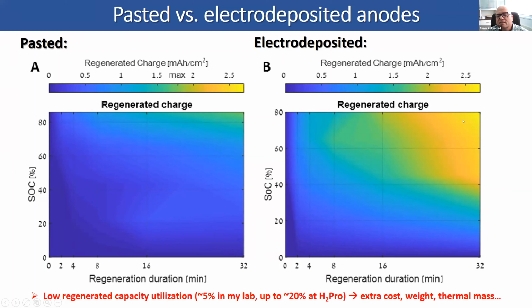But in the case of the electrode deposited electrode, we got nearly 3 times more. Today, we get much higher results. And that is because of this fine structure that supports the effective mass transport. But still, we have an issue with material utilization. We don't use all the deposited material. In my lab, we use about 5%. So we have relatively low material utilization.